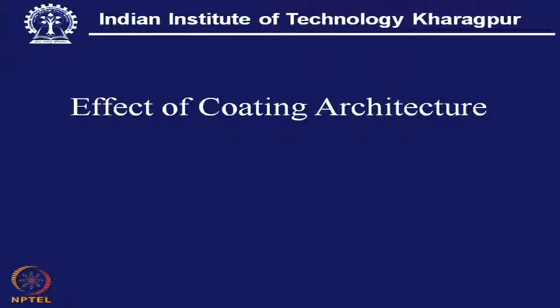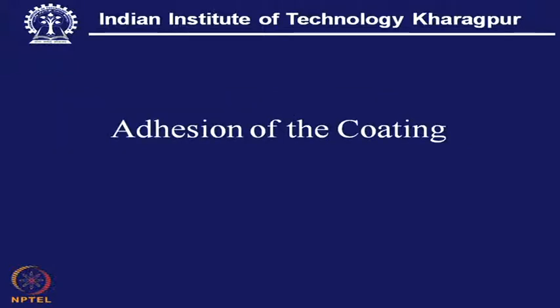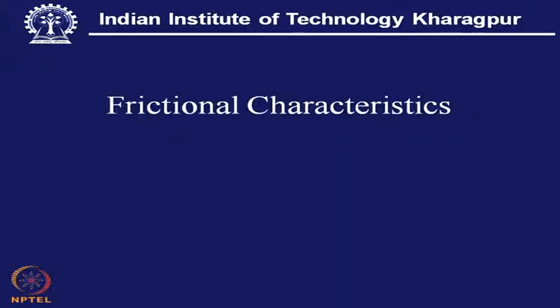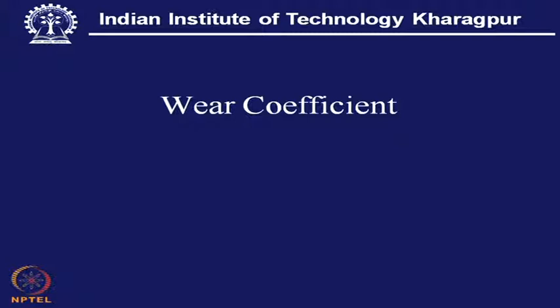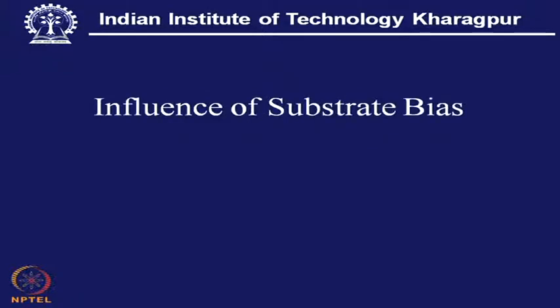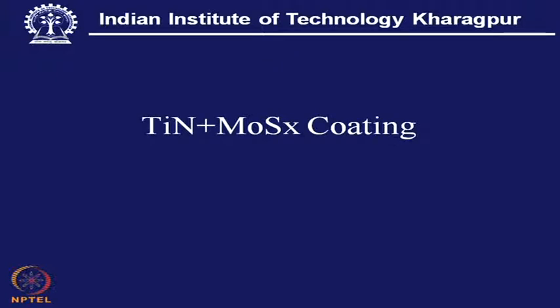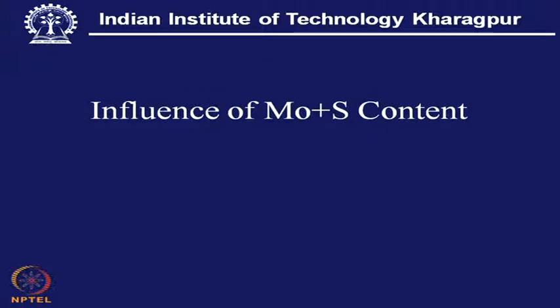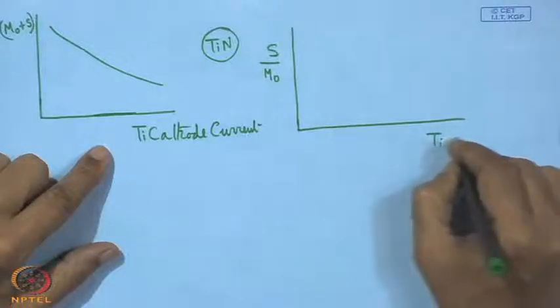What we have seen so far is the effect of coating architecture that we have just discussed. With this, we found that this MoSx plus titanium nitride coating architecture gives the best overall performance in terms of adhesion, hardness, frictional characteristic, and wear coefficient. Considering all this, we saw that this is the best overall performance. Now, what we can find here is the TiN MoSx coating, and the influence of Mo and S content, also with Ti cathode current.